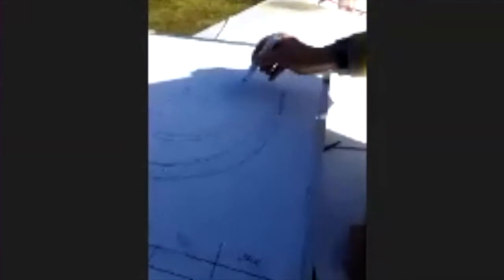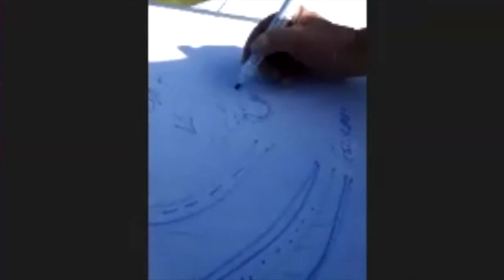So in Steve's boat here, there are 3 beams that run fore and aft underneath that. They're like what's called a top hat section. So they've moulded in there with fiberglass over the top of them, and typically you get stress fractures around the edge there. It works around the edge there, and the stress fracture appears on the outer skin out here. Generally, they're not a big deal, but on these boats with very thin laminates, you'd want to be pretty careful with it. You'll probably find you'll have stress fractures for a long time, and then one day it'll crack somewhere all the way through. So you can keep an eye on it. I wouldn't bother trying to fix them if they're there generally. It's just too much work. They'll probably keep coming. Perfect.